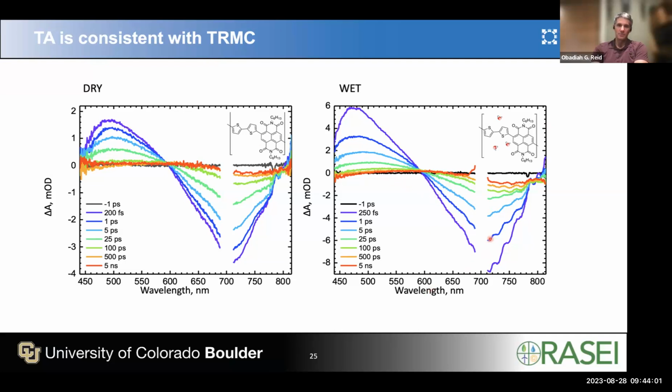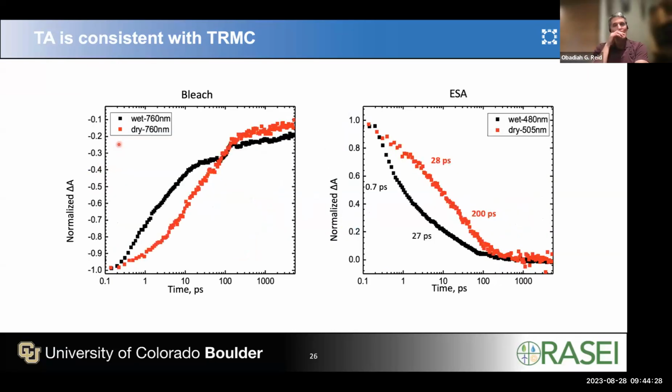Otherwise, things look pretty similar. However, what you do notice is that in the presence of water, the bleach seems to be longer lived. And if you look carefully, you'll notice that the rate at which this excited state absorption is decaying in the presence of water is quite a lot faster than it is in the dry case.